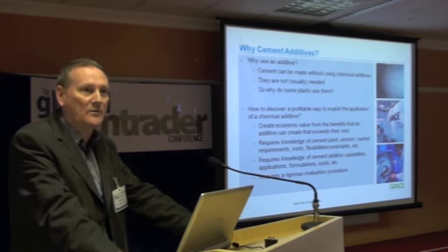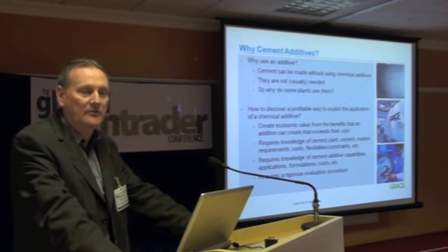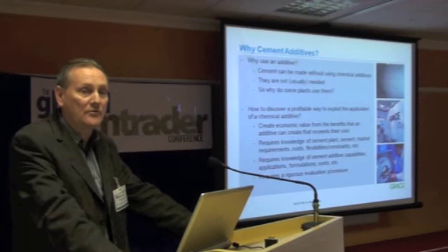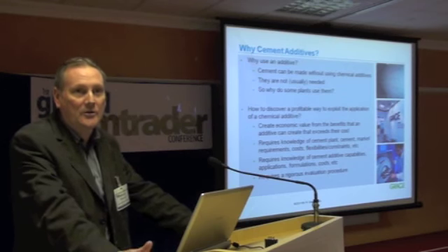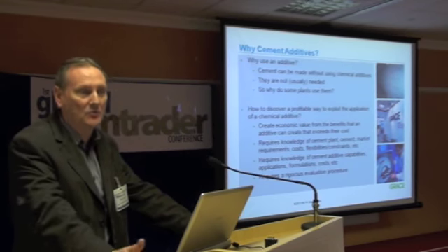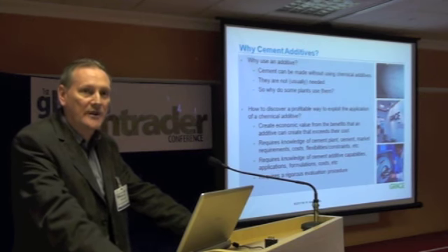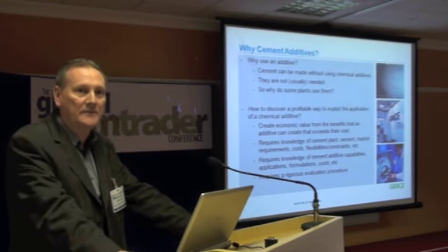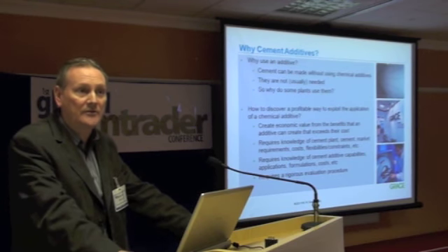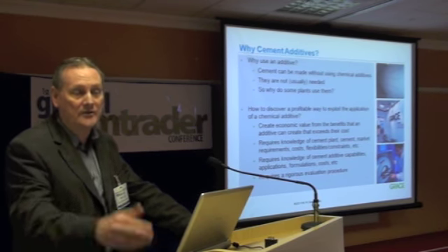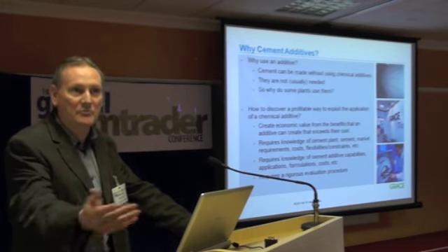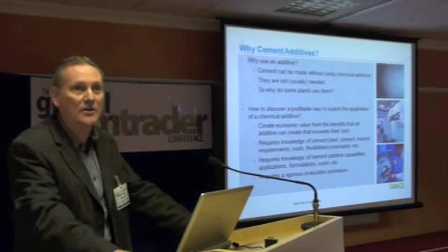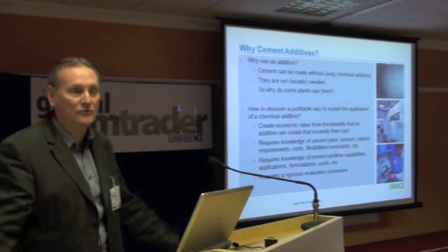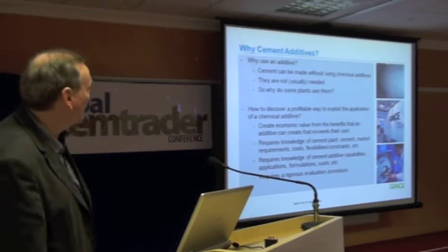North America is one market where virtually all the cement uses some kind of chemical agent. It's mainly there as a grinding aid, but mainly to improve the flowability of the cement for distribution purposes. Anyone who knows unloading compacted powders knows they obtain a cohesive strength, and when you treat them with a chemical in a grinding process, in the case of cement, you actually improve the unloading times. You reduce the unloading time from ships, from rail cars, and from road tankers. And of course, you can do the mathematics. It can have an impact on distribution costs.